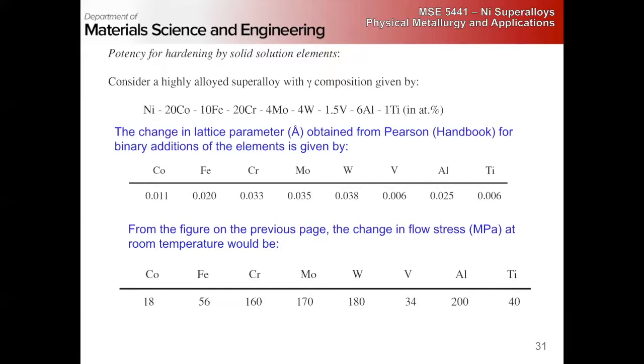And we can look at the change in lattice parameter for all the different elements. And we notice something really interesting here. If we look at aluminum, it is predicted to have the largest effect when you take the modulus effects into account as well, right? So in principle, aluminum would be a great solid solution strengthener for the gamma phase. The only problem is, where does it go? It partitions to the gamma prime, right?